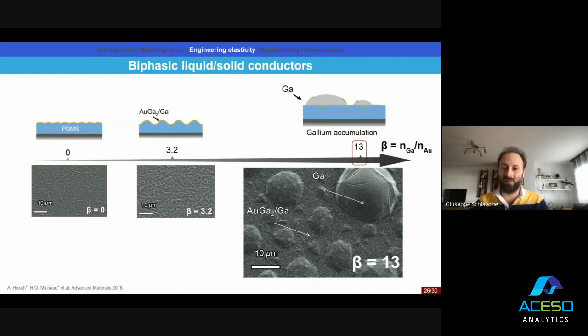If we deposit gold and then gallium on top of the gold, we get the formation of what we found to be biphasic liquid-solid conductors. In other words, the gold acts as a solid base on the PDMS, and the gallium on top acts as a liquid parallel conductor.